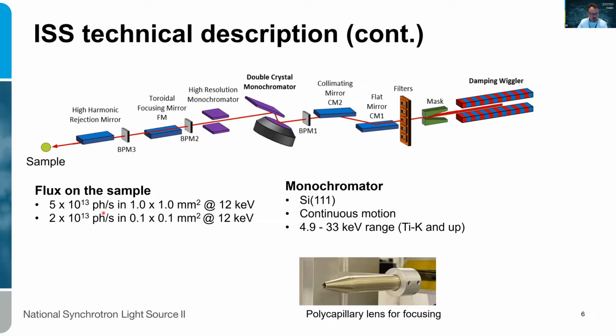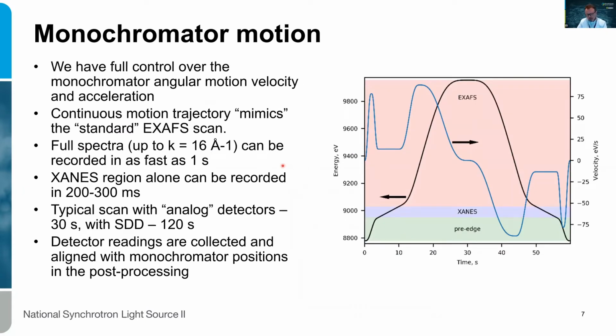monochromator. But we are in the range of several 10 to the 13 photons at the sample with the unfocused beam. We cannot use the regular focusing solutions for a device that's so long, it's 7 meters long. So we're using this polycapillary lens for focusing into a beam of 100 microns, where we lose about 60% of the intensity, but this is still more than enough for many applications. And the energy range, just the standard thing, covering from titanium up to about 33 kiloelectron